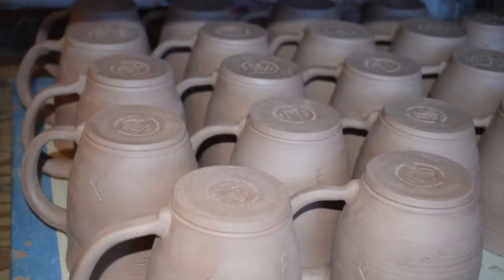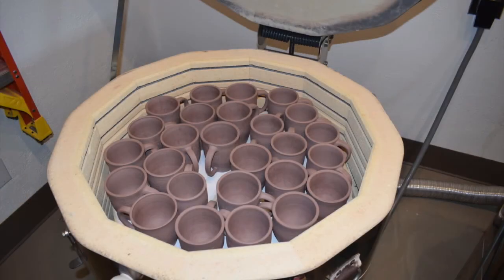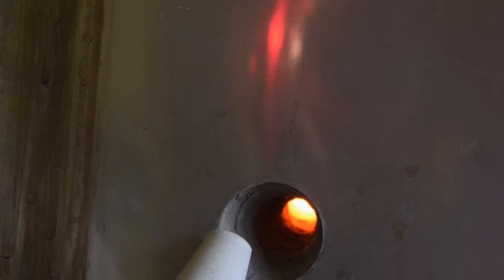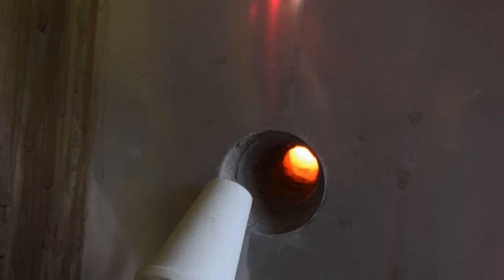With all the wet clay work finished, the mugs are placed top down on drywall board to slowly dry to the bone dry state in preparation for bisque firing. The mugs are loaded into an electric kiln in several shelf layers where they will be fired to over 1,900 degrees Fahrenheit over a period of approximately 10 hours. This image shows a pyrometric cone pack with two cones — O5 and O4 — which serve as a critical guide to the kiln operator in measuring the kiln temperature. When viewing the kiln interior, it's necessary to wear protective eye gear and heavy gloves.